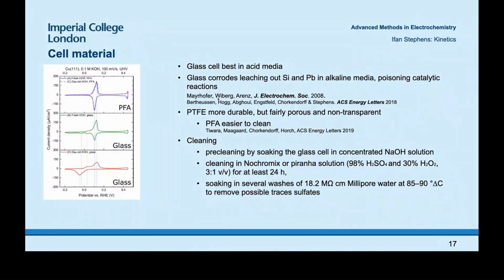An alternative would be to use PTFE or Teflon cells. They don't corrode in alkaline media. The only problem is they're fairly porous, so often if you have contaminants around, they get stuck and leach out in the next measurements. Also, PTFE cells are not transparent, which can be a pain if you're used to working in glass. Some of my former colleagues at the Technical University of Denmark proposed instead to use PFA. These are some cyclic voltammograms they did of a copper single crystal in PFA relative to glass. They found much sharper peaks, and they attributed this to the PFA being a lot cleaner. Generally, cleaning itself is also really important, especially if you're looking at very low surface area electrodes.